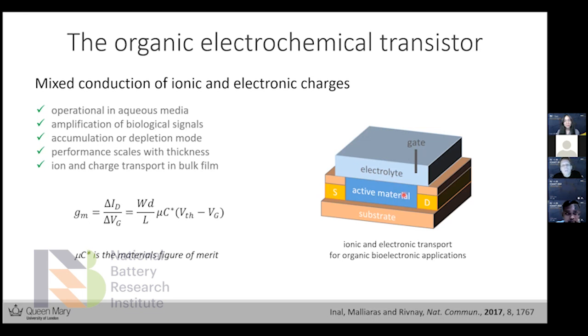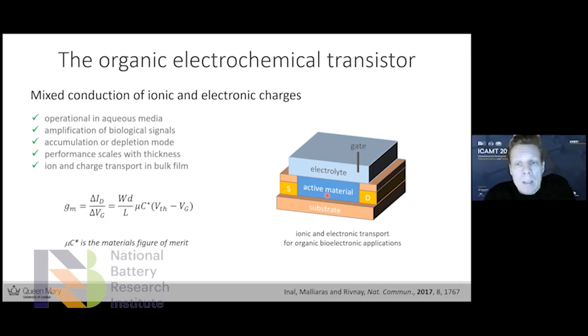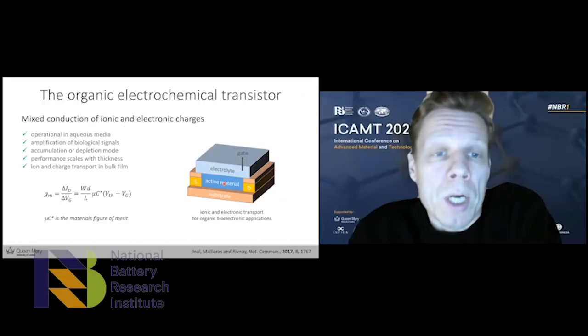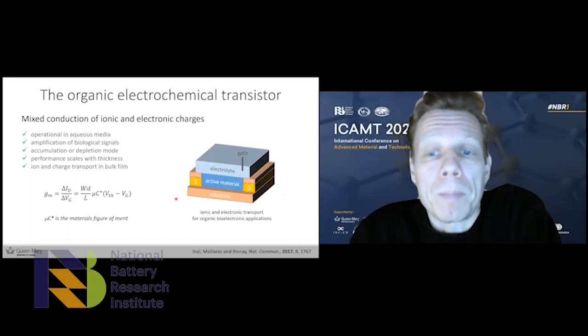And quite importantly, the performance scales with the thickness. So we can tune the performance by tuning the area, the volume of the active material, which is the organic semiconductor. And as I said, we have both ions and electronic charges playing a role in the charge transport in the bulk film.